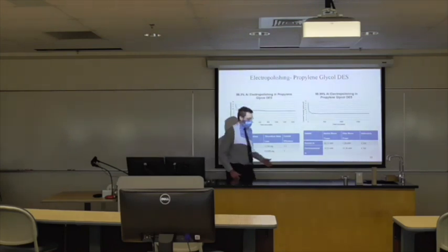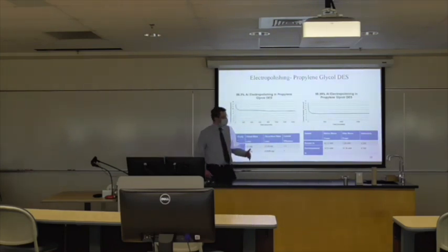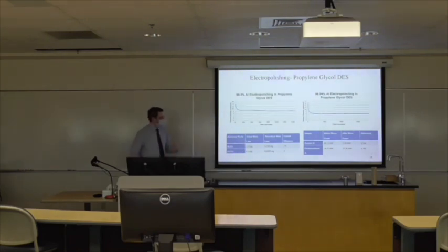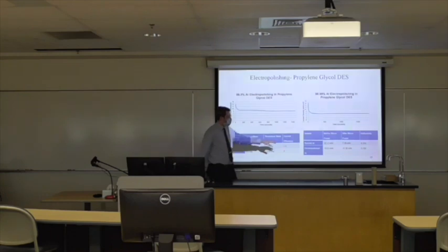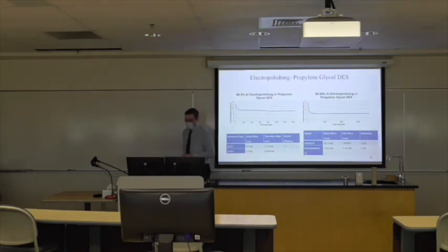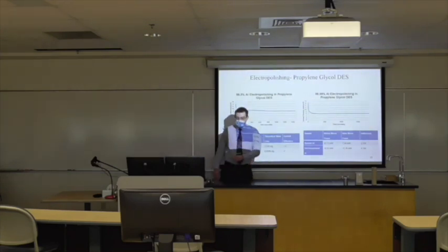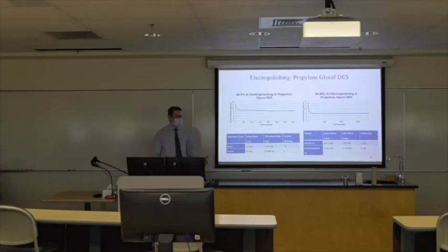So when we place the detector before the aluminum and the laser goes to the detector, as well as after the aluminum, we get these two sources, and we can see from that ratio that the reflectivity of the sanded aluminum is about 36%, versus the reflectivity going up to 78% for the electropolished aluminum at 99.5% purity. You would expect, with more time as well as higher purity aluminum, that these numbers would improve even further. So, the electropolishing of the aluminum works.